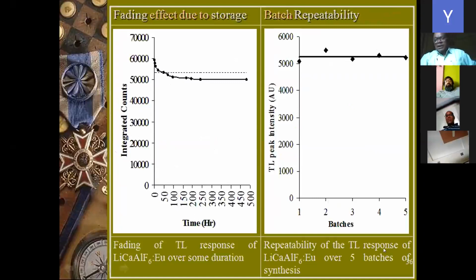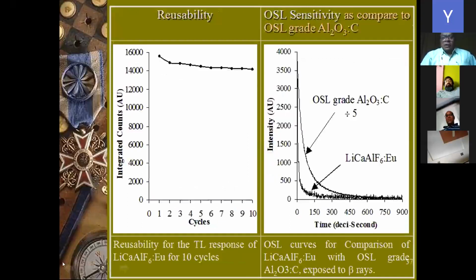Repeatability of the TL response is being seen on LiCaAlF6:Eu for 5 batches of 30 grams each. We have prepared 5 batches of 30 grams each after a particular interval, and we see the performance is consistent. Reusability of the TL response.